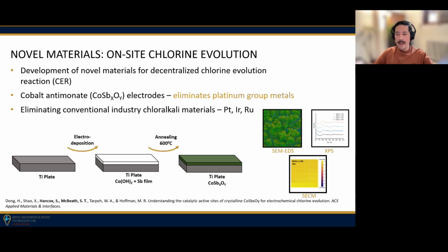How do we do this? So we have a substrate material, like a titanium plate, and then we put all of our cobalt and our antimony, we dissolve it in water, and we electrochemically deposit it on our titanium electrode or substrate. And then we take that and we put it in the oven and we anneal it. So kind of a fancy word for crystallizing it on the electrode surface.